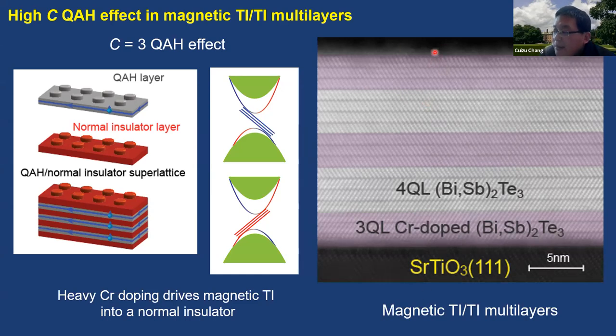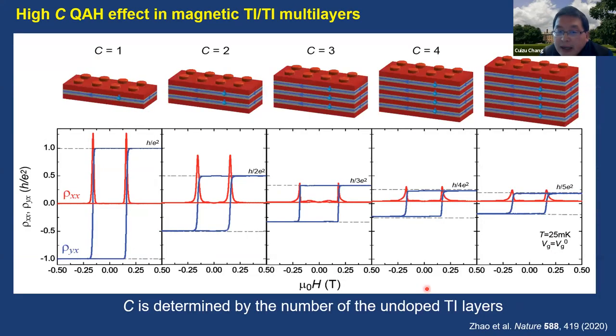And from the TEM image, we can see the magnetic TI and TI multilayer sample with a highly ordered lattice structure. And we fabricated the magnetic TI and TI multilayer samples with 1 to 5 periods. This is just a sandwich structure, this kind of layer structure. And we also performed the transport measurements.